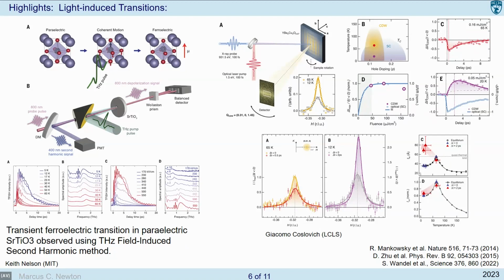On the right-hand side here, we have another study more recently performed looking at superconductivity in this yttrium barium copper oxide material. And in this case, we're actually probing with X-rays. We pump with an optical laser, and we probe, and we simultaneously look at the charge density wave order and also superconductivity in the material. The main result was the ability to see how superconductivity and charge density waves interact with one another, and how you're able to selectively quench certain modes to reveal that interaction. And that was quite key.